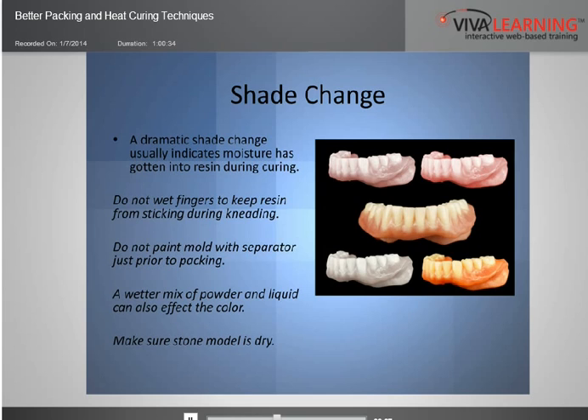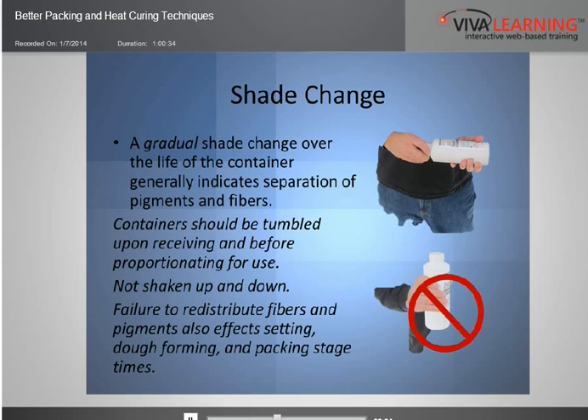You know, the calls are, I've been using it, and now I notice that it seems to be lighter, it seems to be darker, it seems to be a different shade of pink, it seems to be orange, whatever. Generally speaking, I have found that 80 to 90% of the times, and the other 10 to 20% of the time, I can't put my finger on it, it's because the containers come and you don't shake, you don't mix them before you start to proportionate.